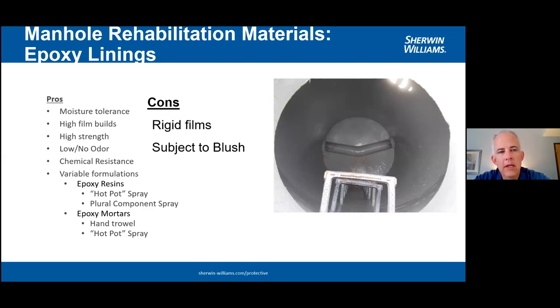The pros of an epoxy lining is they're moisture tolerant. Concrete, we all know, is very difficult to get dried out in a below ground area, especially where we have water going on and all the different things that we have to deal with whenever we start coating stuff below grade. Epoxy linings can coat over visibly damp concrete. So they adhere well, it does not hurt the performance characteristics of them, and it makes them very much easier to install. High film builds, high strength, low odor, and chemical resistance. There's a couple of different formulations to where this stuff can be sprayed or hand troweled, and I'm gonna show you a video upon the completion of this, a video of where we mixed up some and we hand troweled it.